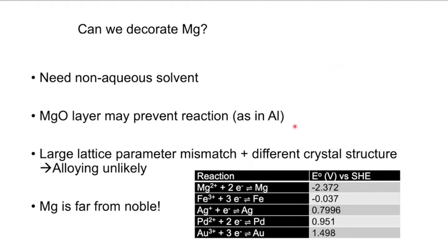You can imagine that in magnesium it's not, otherwise I wouldn't be talking about that. Another issue is that there's always a large lattice parameter mismatch and often a different crystal structure between magnesium and the metals that we're trying to replace with. It's not clear whether we're going to get alloying. Magnesium and silver do alloy, but the other metals is not as likely. But the saving grace here is that magnesium is really reactive.